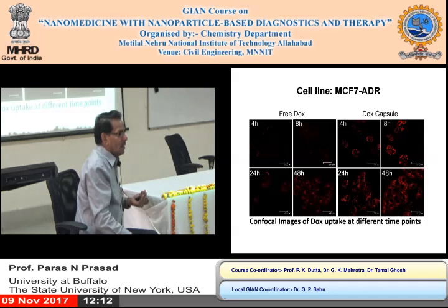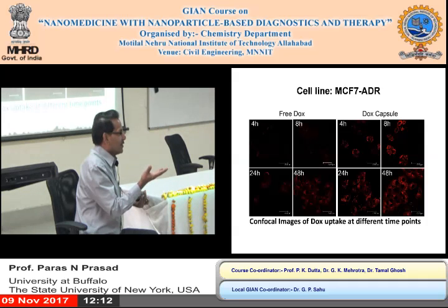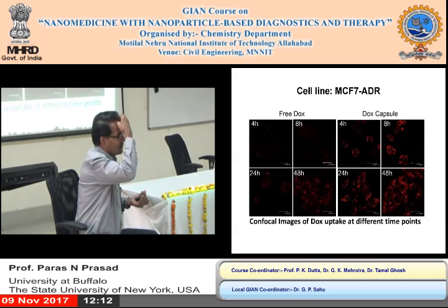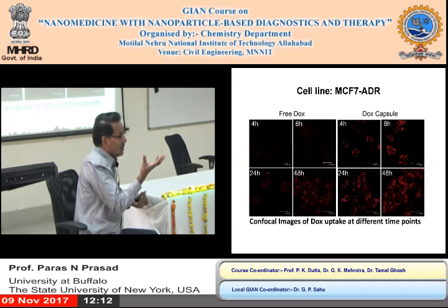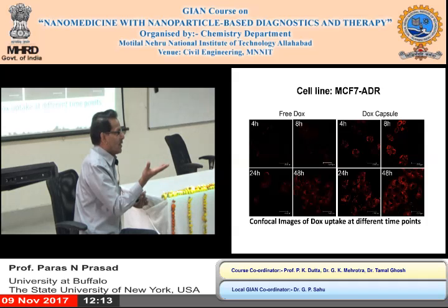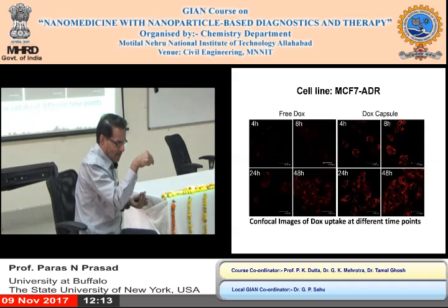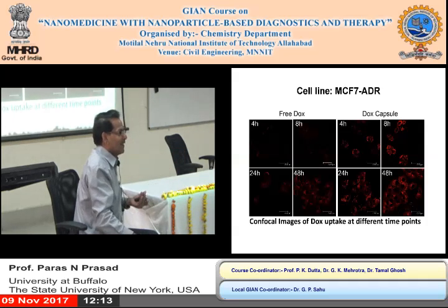Quantitative could be that you dry the cell sample and you can do mass spec analysis. Inductively coupled mass spec analysis we do routinely. Then you want to find out how much of the nanoparticle is inside. You can also do TEM on the dried sample and count how many nanoparticles are in there. Are there many, or one or two? So these are quantitative characterization of cellular uptake.